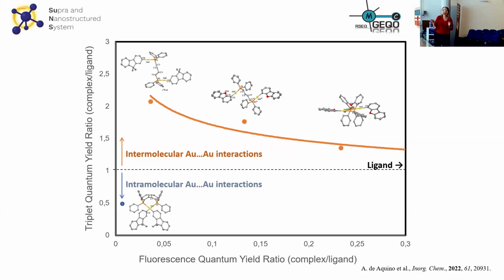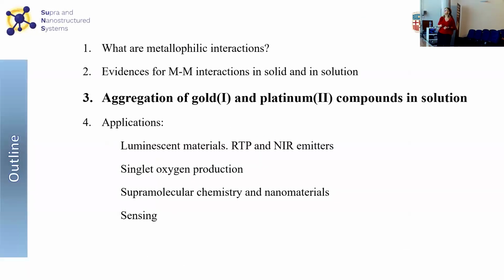And what we observed is that, in fact, the higher emission quantum yields happen when we have intermolecular interactions, while the presence of intramolecular interactions favors the non-radiative processes and decreases the emission quantum yields. Okay? So we could observe this with two series of compounds. It would be interesting to see if we can extrapolate this behavior to other types and make a general statement. But at least for these two series of compounds, we can observe this difference in the quantum yields depending on if we have intra or intermolecular contacts.